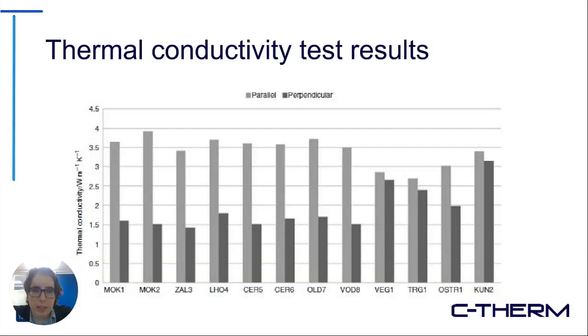So you can see on this plot the anisotropic thermal conductivity behavior of these different slate samples. Some of them are quite anisotropic, with the in-plane direction being twice, or sometimes closer to 1.5 times, as thermally conductive as the through-plane direction, and I believe in one case it's over twice as thermally conductive with the MOK2 sample. So what that shows is that these materials are much better at spreading heat than allowing it to penetrate through the plane of the material.